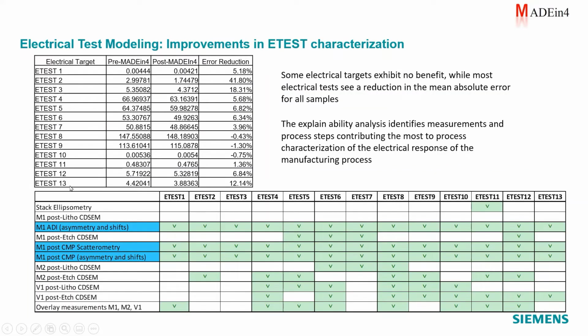In this particular case, there are 13 different electrical tests. So what we can actually see here is that if we take a look at the best performing case, for this e-test 2, the error reduction applying the technique is about 41.8%. It gives us an idea of what are the main contributors to all of these different e-test conditions. These three different metrology steps are consistently measured in the top 20 most important contributors.